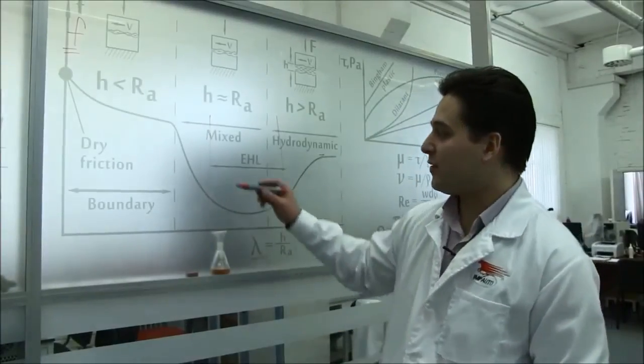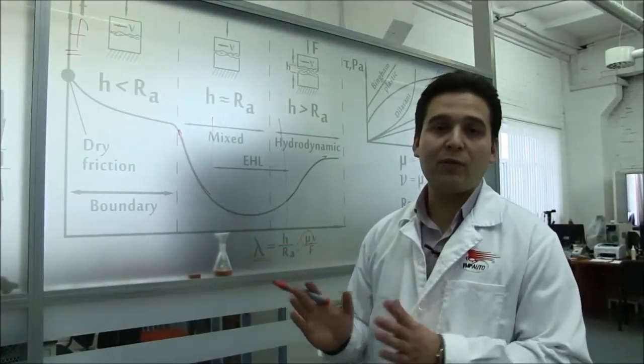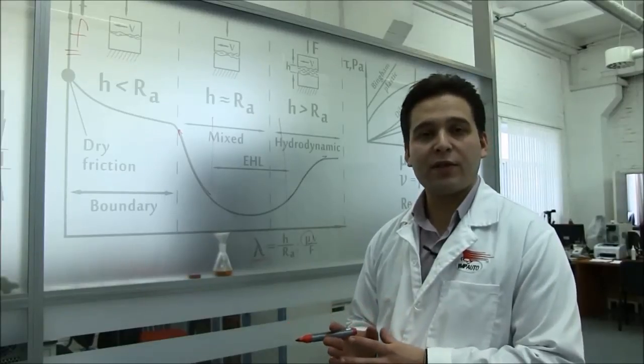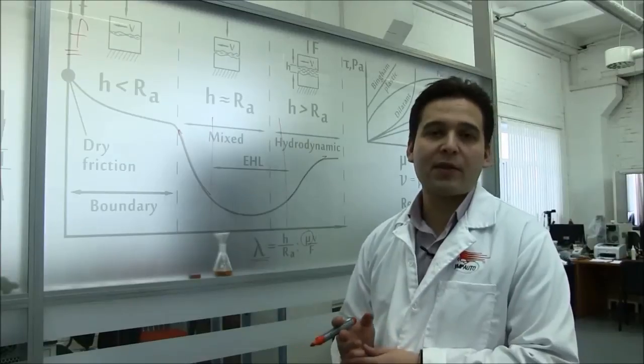If the HTHS decreases, it can result in the loss of the oil layer and intensive wear of parts. The decrease of the HTHS happens naturally in case of mixing oil with fuel or destruction of oil molecules.